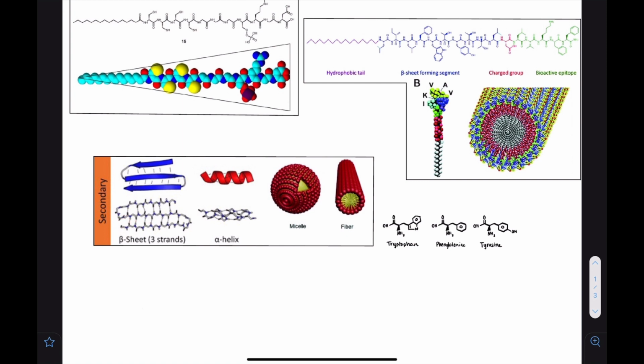Alongside hydrogen bonding, hydrophobic interactions are also integral to the formation of these assemblies. Increasing the hydrophobicity of a molecule by decreasing the hydrogen bond forming ability of solvents directly leads to aggregates. Put this molecule in a polar solvent and now you have a micelle. What if your peptide moiety has additional non-covalent interactions? Now you have a cylindrical micelle.